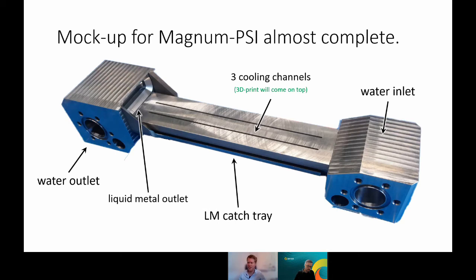Maybe I don't think everybody knows this, but tin and lithium melt at roughly the same temperature, right? At 180 degrees for lithium and 230 for tin. But tin does tend to evaporate much less easily. That is why you can have some higher surface temperatures with tin, also in a reactor. But that is at the same time the reason why it might not be as resilient to disruptions as lithium, because you need a much higher temperature to evaporate sufficient tin. And maybe that temperature is in excess of the tungsten melting point. I don't know, but it's possible. So we will see. I don't know if that answers your question. Yeah, it does. Thank you.